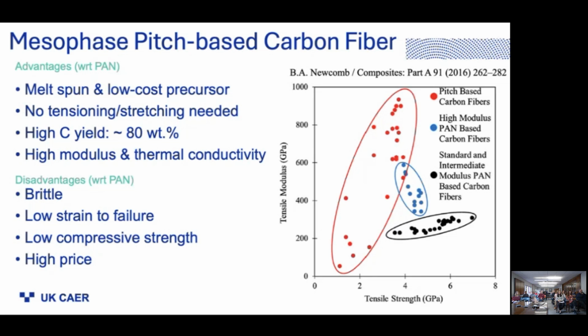80% of the mass converts to carbon. That's good. Really high modulus fibers are capable, you can see in red here. These really high pitch-based carbon fiber moduli can be accessed. And along those lines, high thermal conductivity of those fibers. But disadvantages with respect to PAN is these fibers are far more brittle, far lower strain to failure, low compressive strength, and they have a high price.